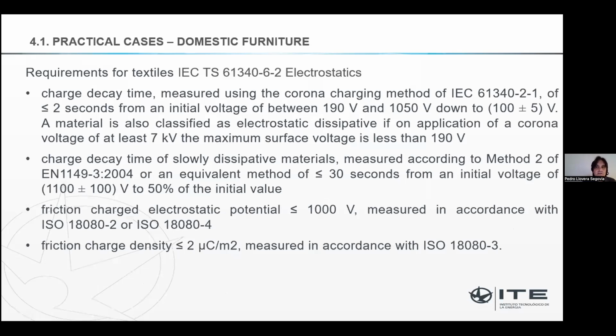In this technical specification, there are recommendations for textiles, which make reference to other standards to measure how good the textile is from an electrostatic comfort point of view. They are related to voltage decay after corona charging, or the use of dissipative materials according to textile standards, or also performing a friction test and seeing if the electrostatic potential is less than 1000 volts or the charge density less than 2 microcoulombs per square meter.